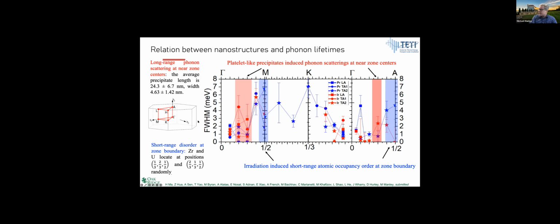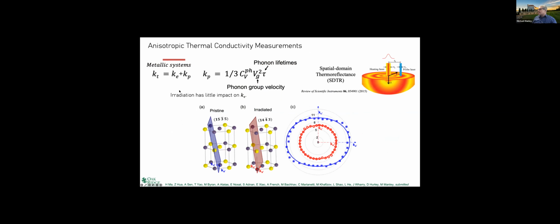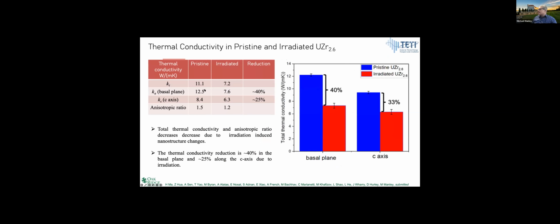So yeah, that's that. We also did some thermal conductivity measurements, and I won't get into this too much here, but the main effect is that with irradiation there's generally a decrease in the thermal conductivity, but the decrease is largest in the basal plane, where we see the biggest drop in phonon lifetimes. But it also decreases along the c-axis, and a general effect is that the material becomes a lot more isotropic. So these are kinds of things we can see. It's a complicated problem, but we can do that.